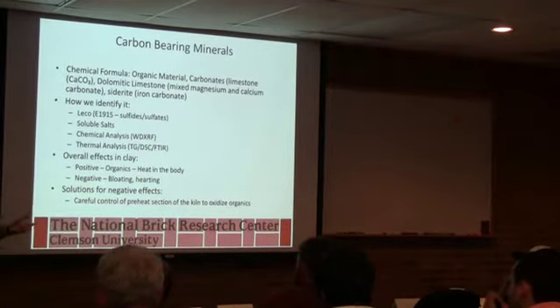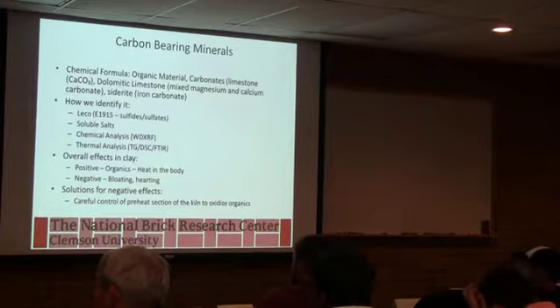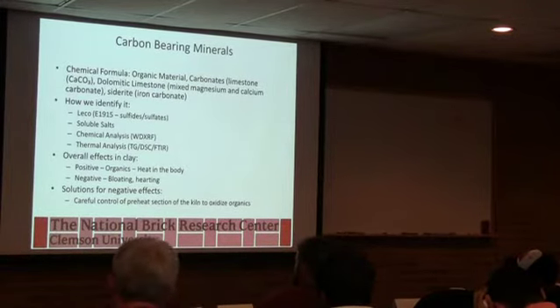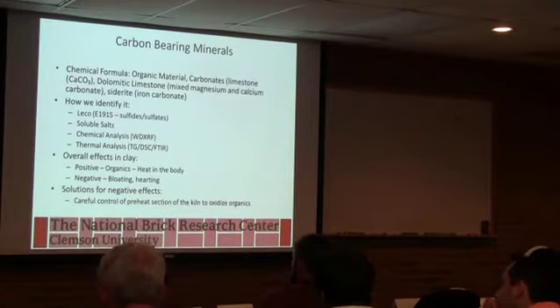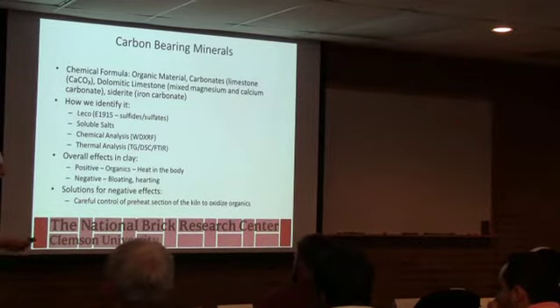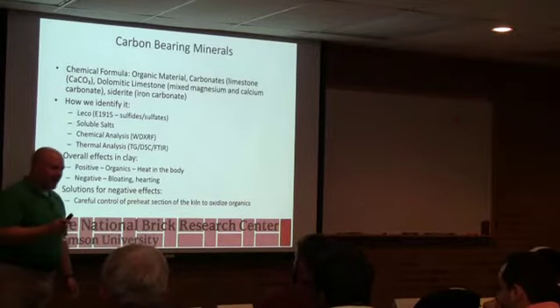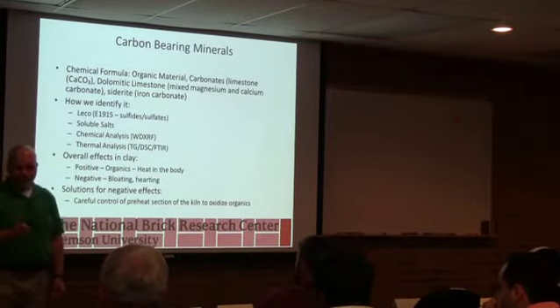So we had one of the kiln manufacturers come in our lab, and actually they modified one of our shuttle kilns to the point where it basically got the brick up to a certain temperature, and there was enough carbon that then it started, instead of metering gas like we do to keep the temperature rise going, it metered air to control the combustion rate.